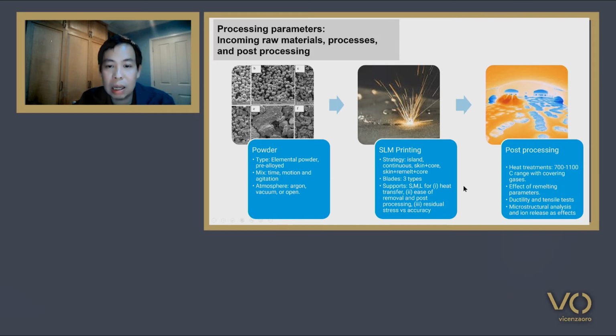And the supports, actually, there are 3 main usages of the supports. First is actually for the heat transfer. We use a lot of supports for the thick parts. And even though we could use a lot, we actually prefer to use few because of the ease of removal and post-processing. So number one and number two are actually fighting each other. If we want really high quality print, we have to spend a lot more time printing, and that's also cost, and also the subsequent problem of a removal process that would take longer. And of course, the last one is the residual stress and accuracy, and this is the combination of both.